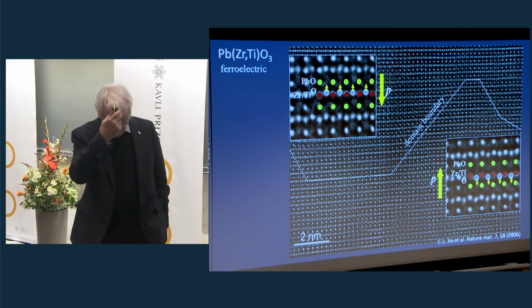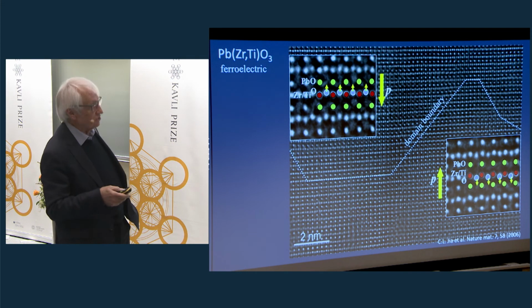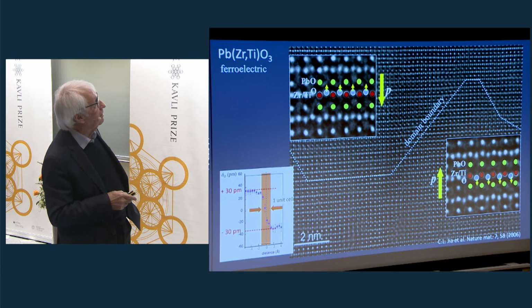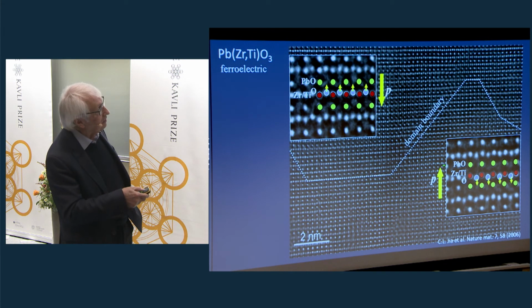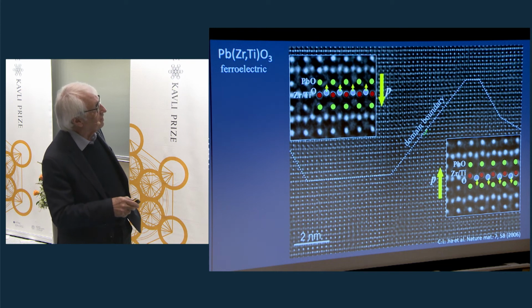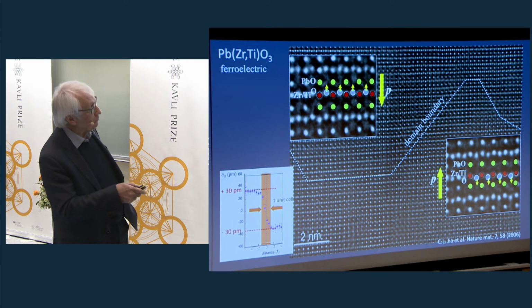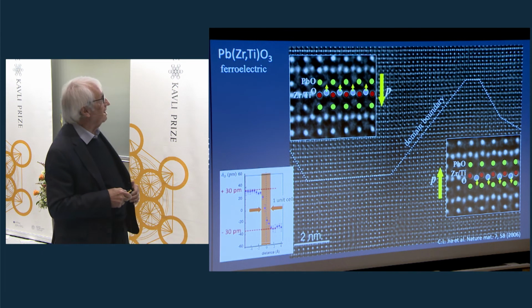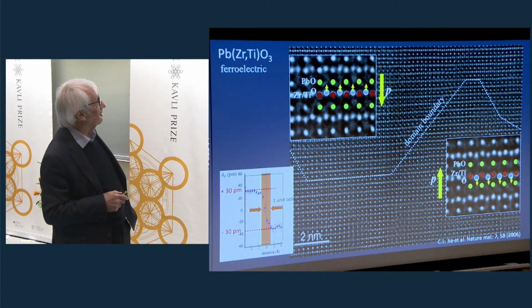And now we look at lead zirconate titanate, which is also a fairly frequently used technical dielectric. And we magnify these images here, and you see directly that the oxygen has moved up here out of this zirconium titanium row. And we now go to the other side here, and we see that the oxygen has moved down. That means we have 2 polarization domains, and this is the polarization domain boundary. And in the boundary, the polarization direction changes on a very short distance, about 1 to 2 projected unit cells.